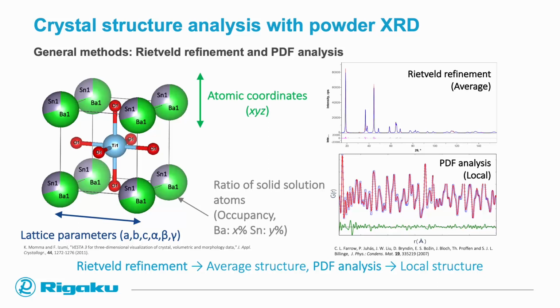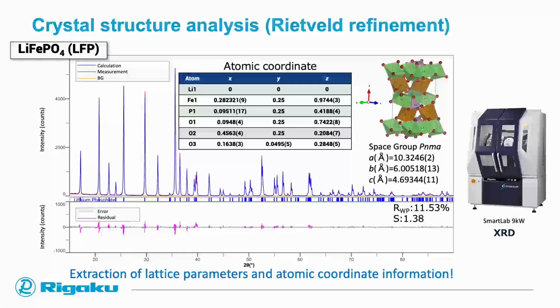On the other side, the PDF analysis offers us information about the local structure of the atoms. So in this case, for example, for lithium iron phosphate, we can precisely estimate, of course, the space group, the lattice parameters, but also the atomic coordinates, which will give us information, of course, about the overall structure, but also probably about the later performance.